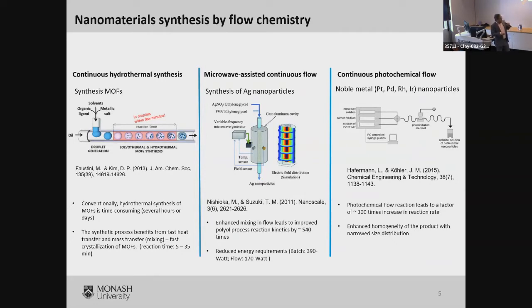Another example is silver nanoparticle synthesis. Here, they've used a microwave to heat up the liquid. You could use a droplet, etc., whatever it is. But the important point is that there is much better mixing and fast mass transfer happening in this reactor. So it's a flow-through reactor with a microwave. And what I want to point out here is in a batch, you need 390 watt energy requirement, and in a flow, you reduce it by a factor of 2 or 3. So that's quite exciting, actually.